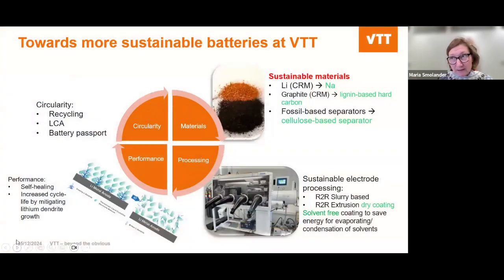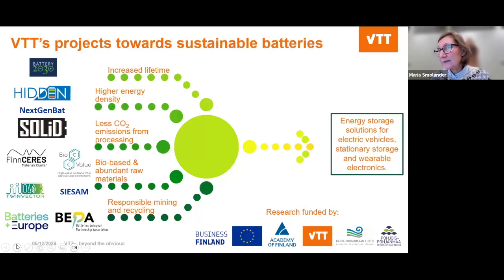And regarding sustainability in this battery area, other colleagues are investigating the circularity. For us, the focus is more on the selection of materials, like replacing lithium with sodium, graphite with lignin-based hard carbon, and also using cellulose-based separators. And then this processing using reel-to-reel printing, also dry coating without solvents, and also what we have been looking at, the increase of the lifetime of the batteries by different strategies which prevent dendrite growth on the electrodes, and this is beneficial for the lifetime of the battery electrodes. So this is investigated in several EU-funded projects.